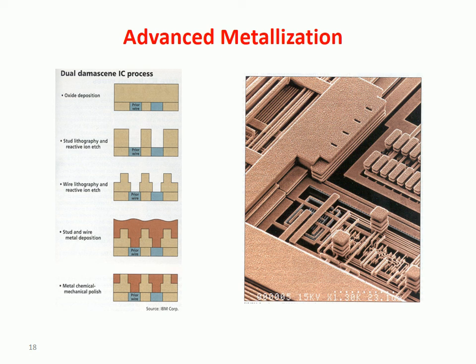And in order to reduce the resistivity of these metal layers, for no more than 10 years now, these metal layers are realized in copper. It's a very difficult process because copper is also a contaminant, so it's difficult to use it and at the same time not contaminate all the rest of the silicon. This is just a picture of a silicon chip in which after the fabrication, all the insulator separating the different layers of metal has been removed, just in order to take a picture.